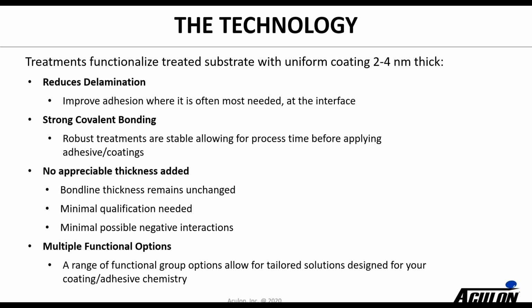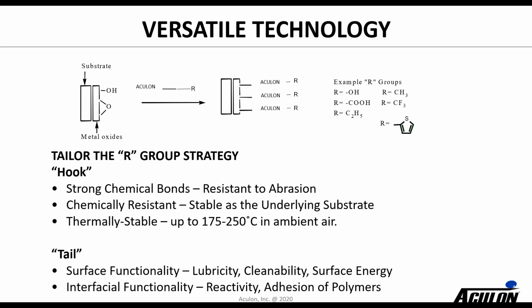And as we said before, the thickness is very thin, which is important, especially for some electronic applications where you're dealing with narrow bond lines, and you just really want to minimize the amount of material that's being used. And the powerful thing about our technology is it's got a lot of functionality. Whether it's the SAMPs, we have 25 to 30 different SAMPs that have different functional groups on the end, and then a broad range of organometallics. So the technology is pretty versatile.